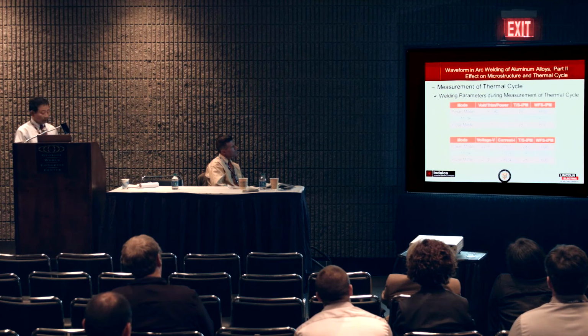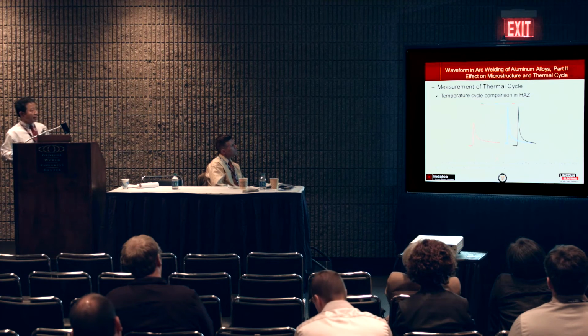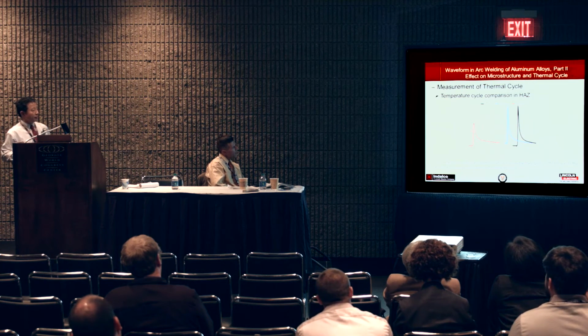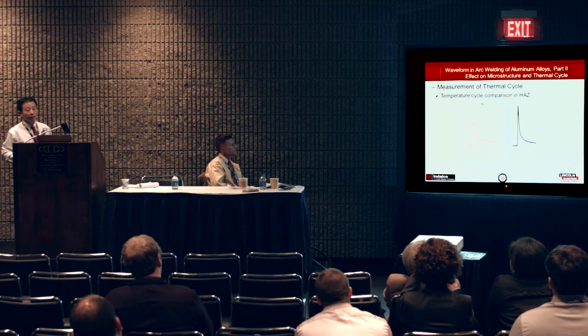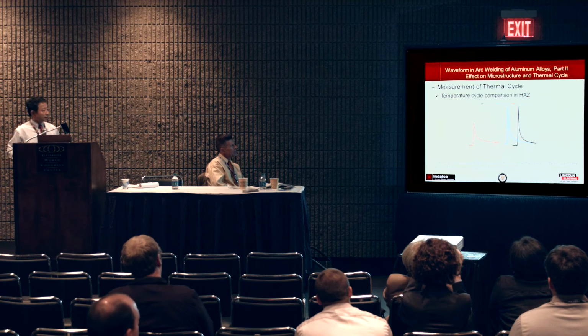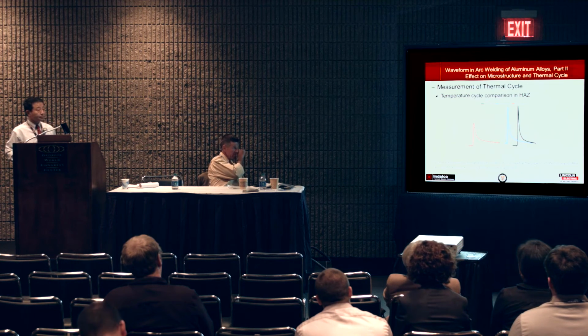And it's very interesting that we found that power mode gives you really, really low temperature distribution in the heat affected zone compared to CV and pulse mode.